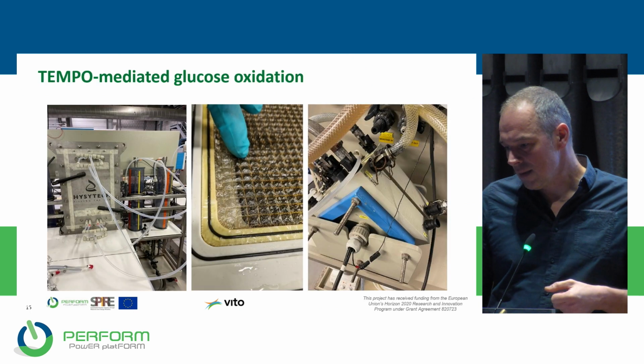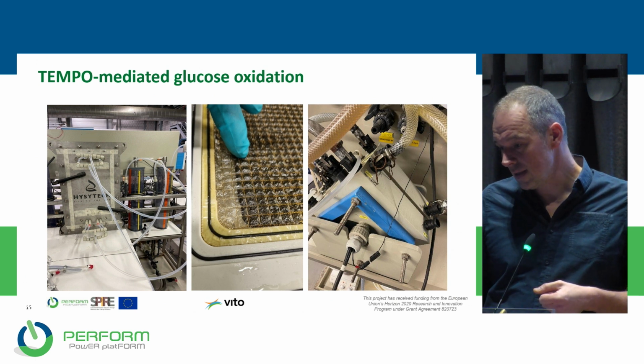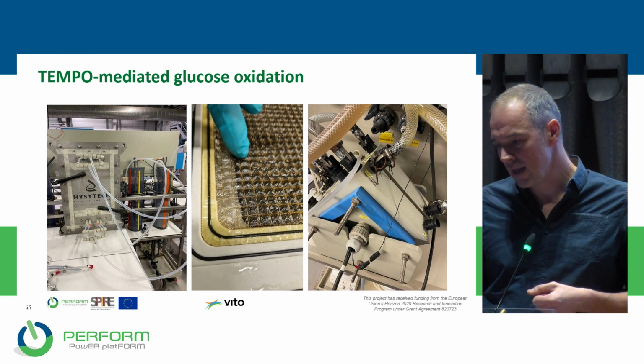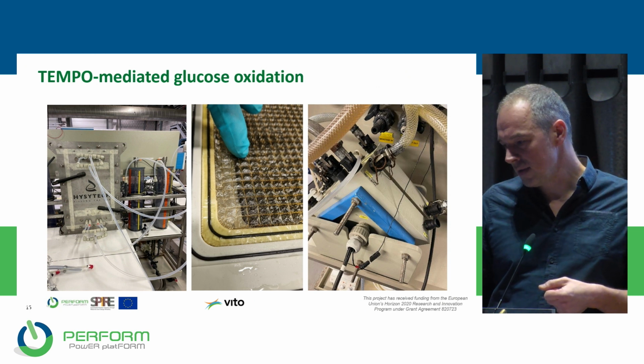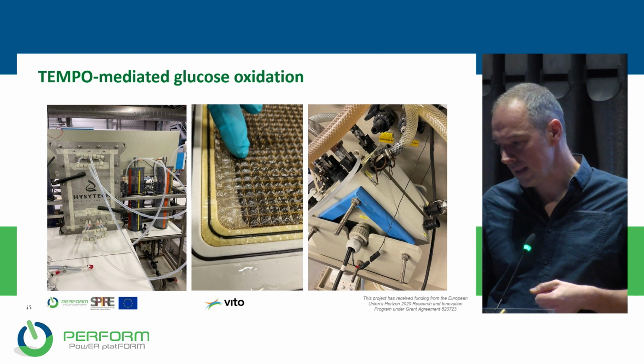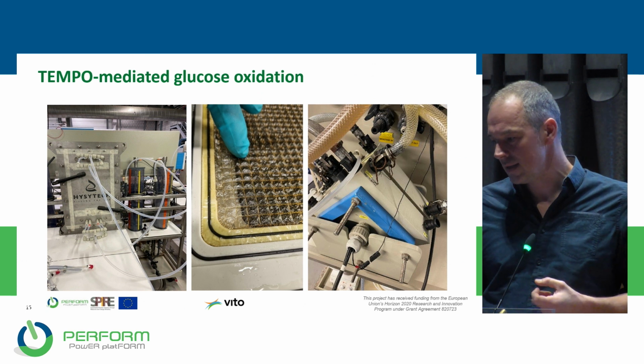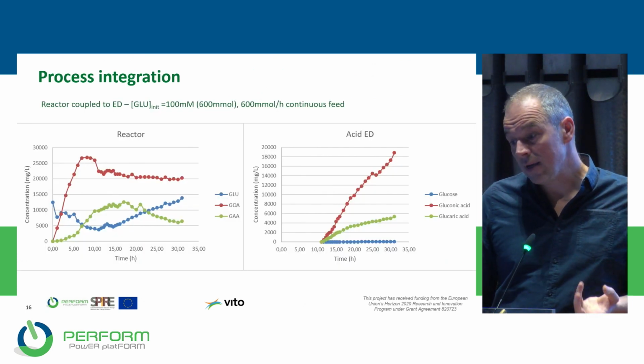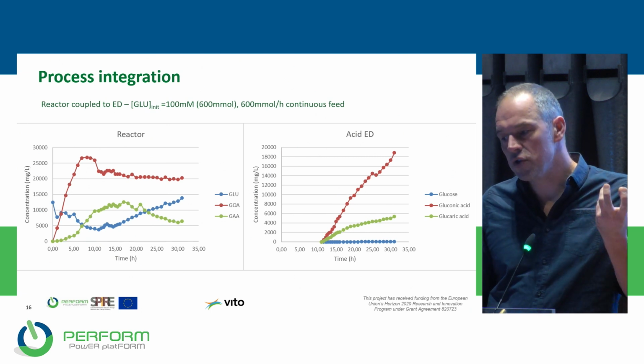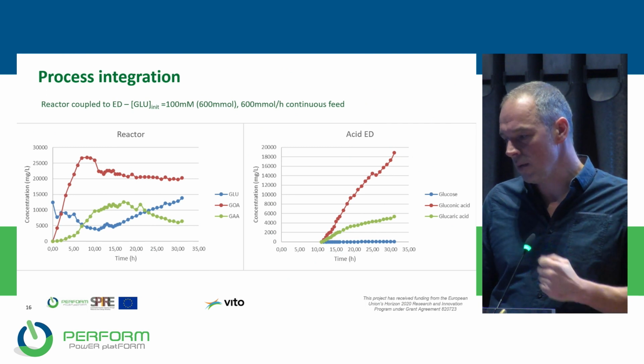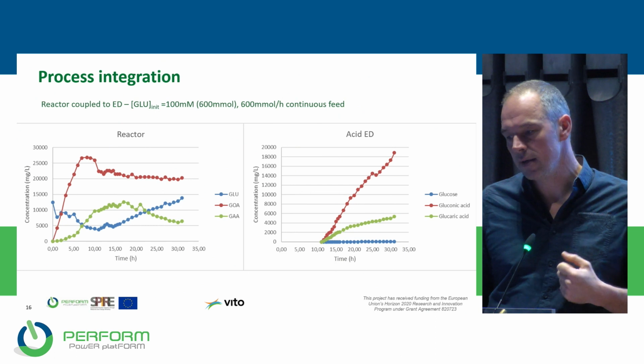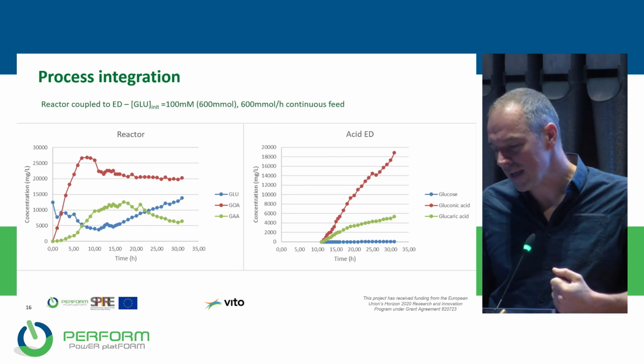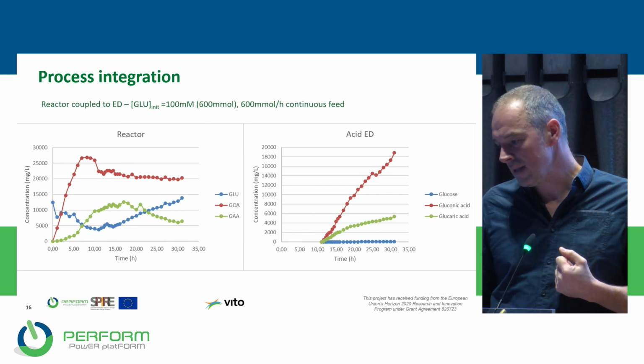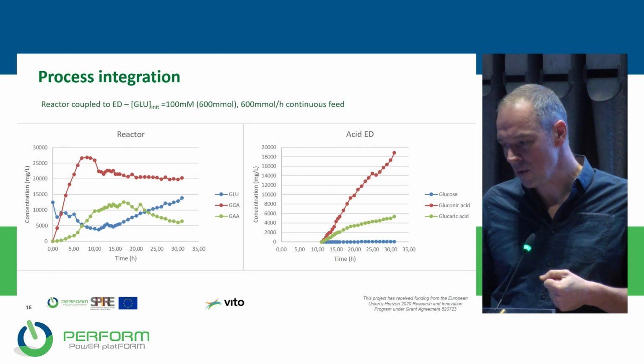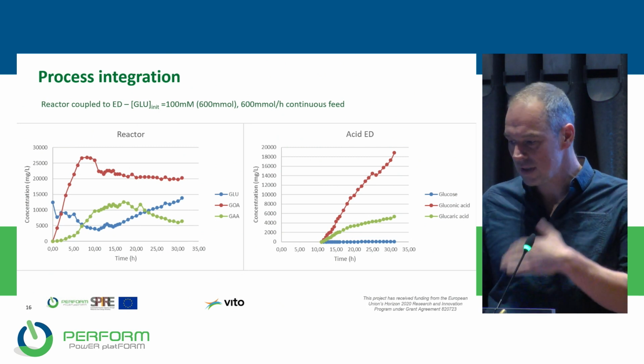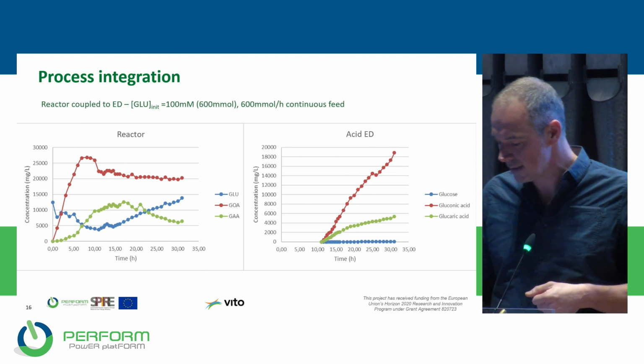So this is what it looks like in the lab. On the left, you will see the cell, so the HYSYTECH 1000 square centimeter cell, the internals in the middle, and then on the right is the electrodialysis cell that basically recovers the acids from the electrolyte. We also did a coupled test just to make sure that whatever we produce in the reactor also ends up in the right compartment. And as you can see here, the glucaric acid concentration is increased in the green one, in the acid compartment of the electrodialysis, as well as the gluconic, but this is because there was no recycle of the gluconic acid.